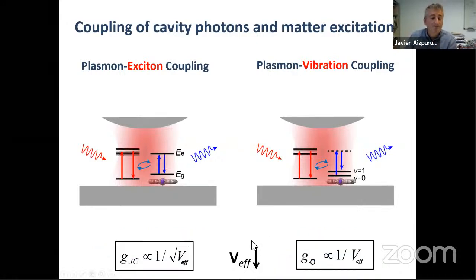And I will show you in a second that this effective mode volume is important and we need to reduce it precisely because the interaction, the coupling strength, both for plasmon exciton or plasmon vibration, is basically proportional to the inverse of this effective mode volume, or to the inverse of the square root of this effective mode volume. This is the coupling strength of plasmon exciton. This is the coupling strength of vibration plasmon, okay? But you see that these interacting energies scale with the inverse of the effective mode volume. So a smaller effective mode volume, more interaction, larger energies of interaction.